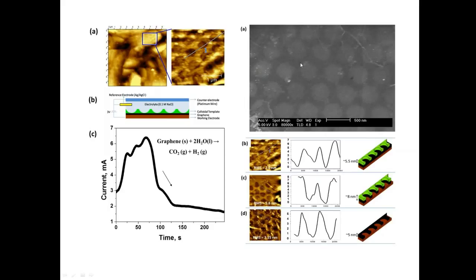So basically the dark region here indicates where we deposited the Carbazole monomer, or rather polymer now, with graphene oxide in the middle of the pattern. So basically, this is a semi-conducting graphene oxide film.